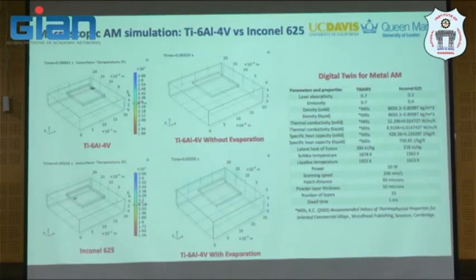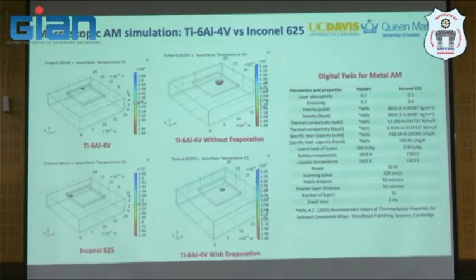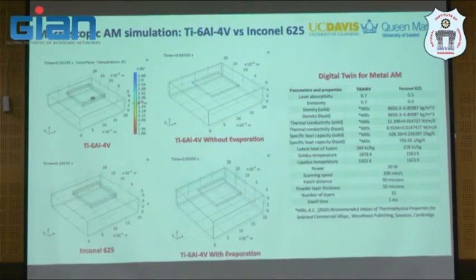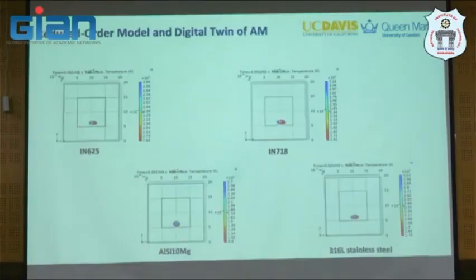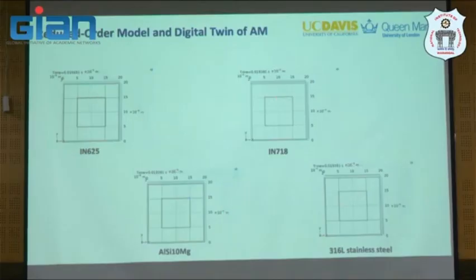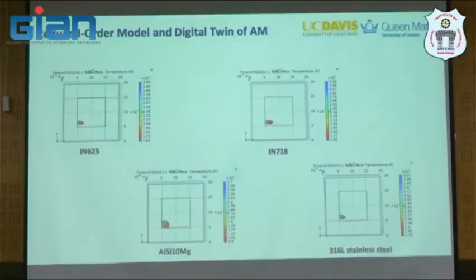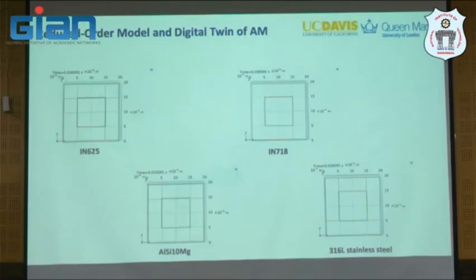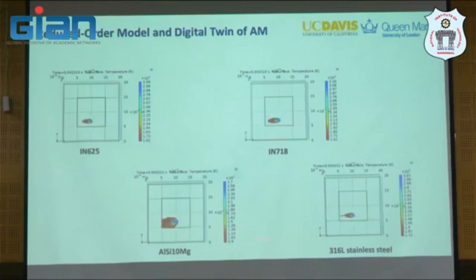Again, this has to be linked some way, somehow with the lower length scale model to translate the knowledge across, so you can probably predict something closer to experiment without any expensive calculation. And then we are looking at this as well for different alloy systems that are mostly used in additive manufacturing now, from Inconel 625, 718, aluminum alloy, and 316 steel. By eye, you see that they're all different sizes of melt pool, just from the change in the thermophysical property. And again, it's not an ideal situation, because each material has different optimized process parameters, but we just show this for the sake of comparison, that you will see that aluminum probably melts a lot, for example.